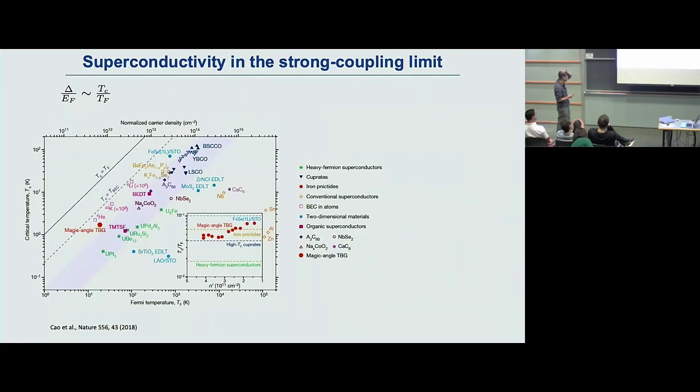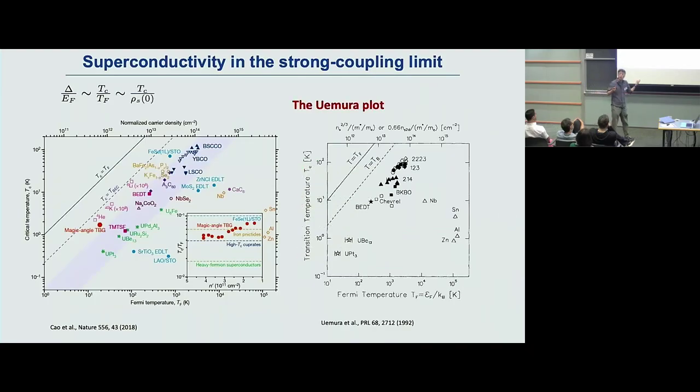graphene is pushed toward the upper left corner, which is usually considered the strongly coupled, unusual side of superconductivity, with this large pair of these things. This is not the first time it's been put up there. This is what is usually called the Uemura plot, starting from the cuprates, right? The cuprate is indeed compared with the conventional superconductor, and goes close to where TC over TF is very large, the right side. I think that's, again, another empirical indication of unusual superconductivity.